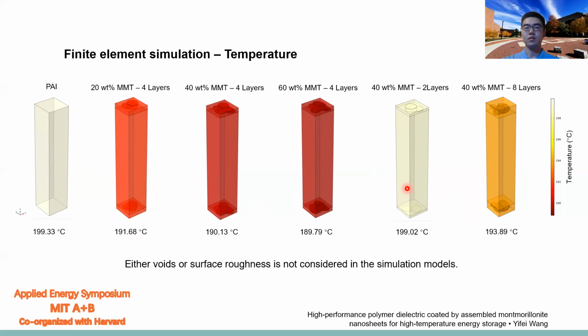But if we compare the samples with different coating layers, we can find that if we just have 200 nanometer coatings, the temperature is pretty high. If we gradually increase the coating to 4 layers, whose thickness is 400 nanometer, the temperature drops about 10 degrees C. But if we further increase the coating layer thickness, we can find that the temperature rises again. So it agrees well with the analysis of electric field distribution that we mentioned in the last slide.